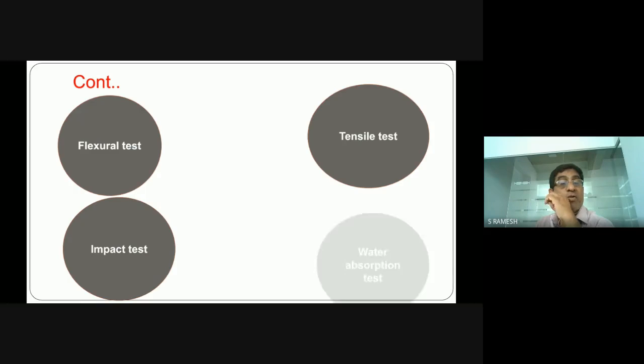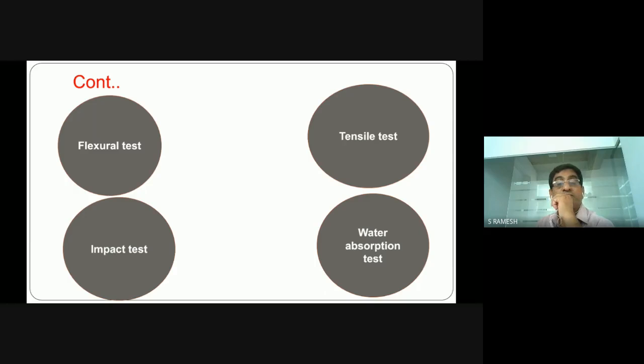And then we will go for the water absorption test. We used the standard ASTM D570. Initially we took nearly 10 gram, and then we went for the water absorption test. We calculate the water gain percentage: the wet weight minus the initial dry weight, divided by the initial dry weight, into 100. I will tell this elaborately during my experiment.